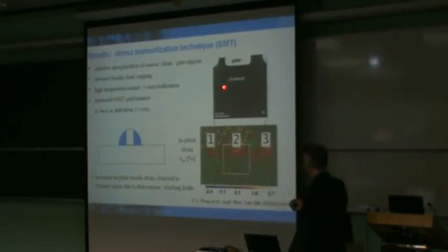And it's through the use of dark field holography, as well as electron microscopy, that we could fairly nicely see that stacking faults were actually present. And these were spanned by dislocations. We either saw perfect dislocations here at the bottom or a combination of the partials that were separated by these stacking faults. But what shows up very nicely is that we can see that there is increased in-plane tensile strain that leads to the improvement in the device.